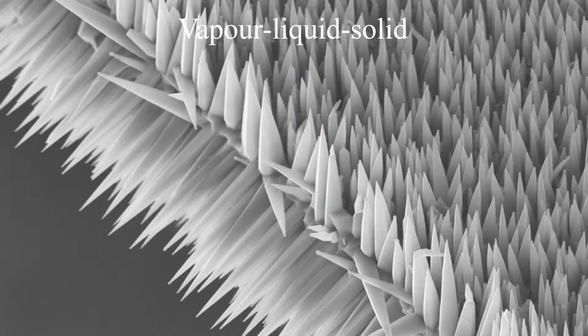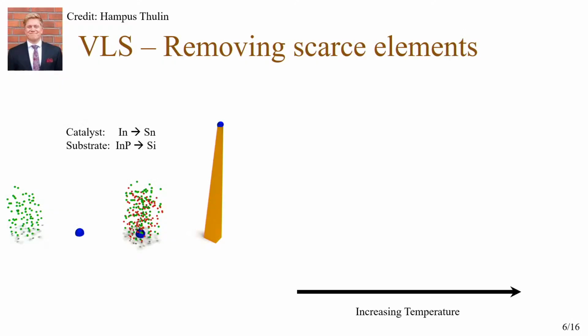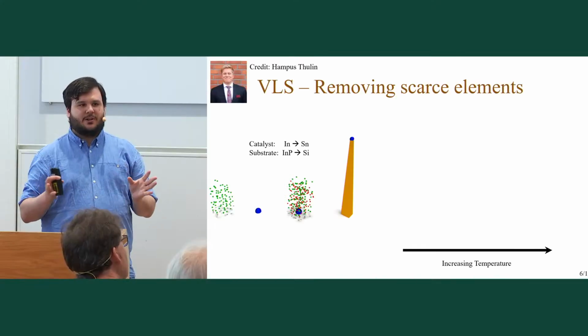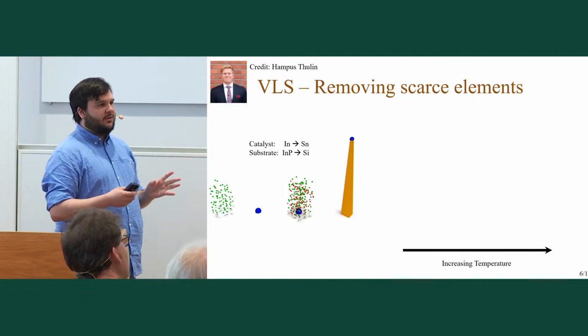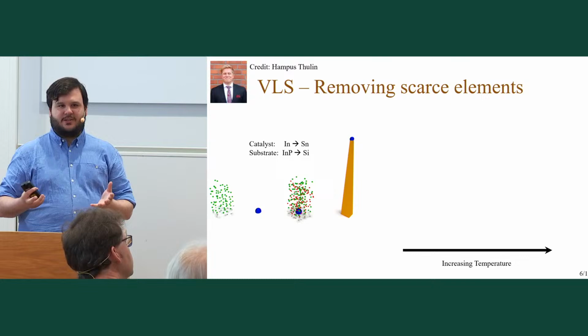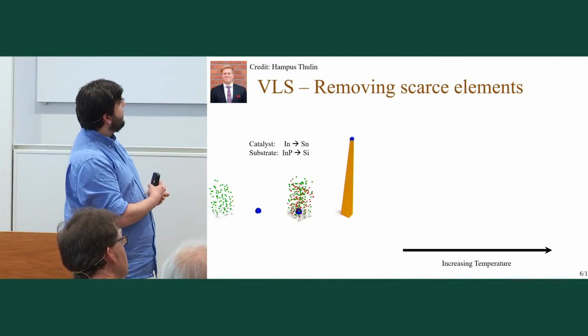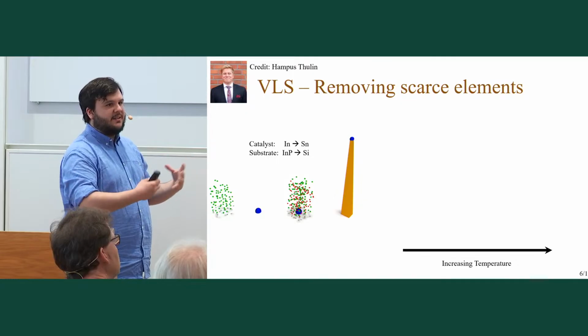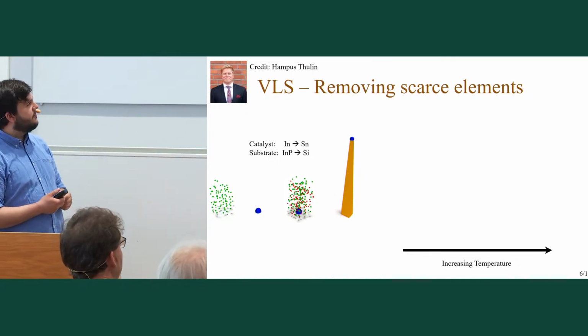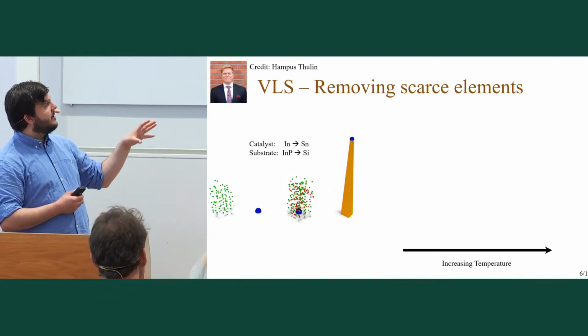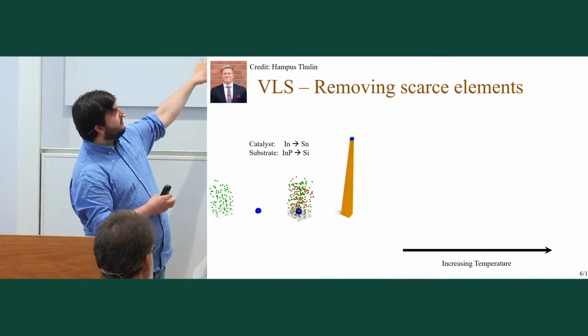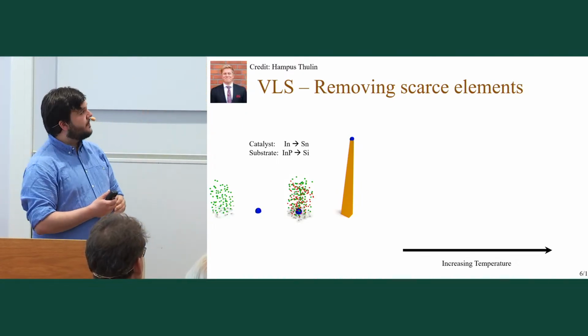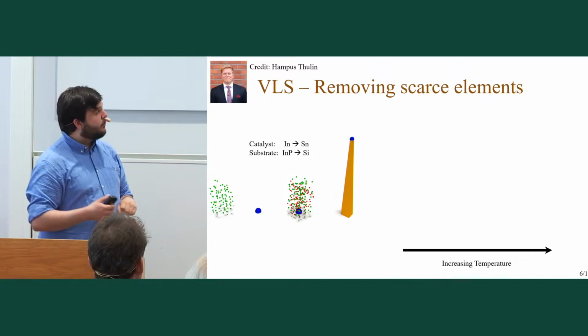Now, I'll very quickly go on to this nanowire bit, because it's not too relevant to the rest of the talk. But what I did together with a recent master student was that we were trying to eliminate all the scarce elements in the process, because even though zinc phosphide is earth abundant and good for sustainability, it used a lot of indium in the process of making this material. So together with Hampus, my master student, we replaced indium with tin as the small liquid particle, and on the substrate that we grew, we started using silicon. And we thought, great, this is going to be a very straightforward process.